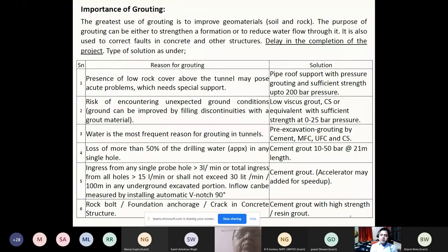Water is the most frequent reason for grouting in a tunnel. In case of water ingress or seepage, first we have to go with pre-injection grouting by cement. If cement is not permeating, then microfine, then ultrafine, and colloidal silica. We can go with whatever material is permeating. Loss of water during drilling, later on we will come to this. Cement grout can be done in this case, and in case of ingress of 3 liter per minute, 15 liter per minute or 30 liter per minute per 100 meter, we can go with the same cement grouting and can add an accelerator to speed up progress.